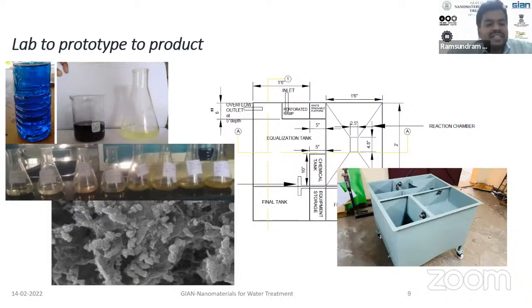And when you ask whether there is leaching after you have coated with polyamide, no. To our understanding, no big leaching has occurred, and it has not been enormously shown in EDAX or ICP-OES. So this is the concept, and this reactor, which has been developed in the lab right now, is in the process of being productized or commercialized for a minor setup of 300 liters per day using a nanomaterial iron oxide coated membrane. And I'm not able to give a lot of particulars because the patent has not yet been awarded. So I'm just giving a grasp of what we have done.